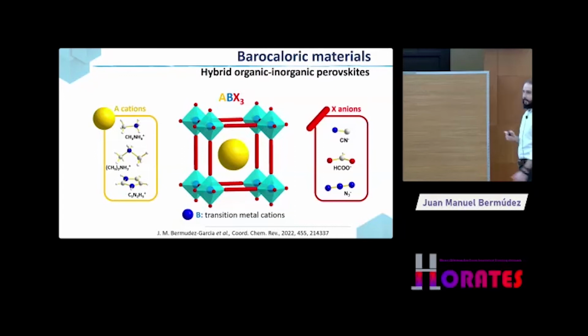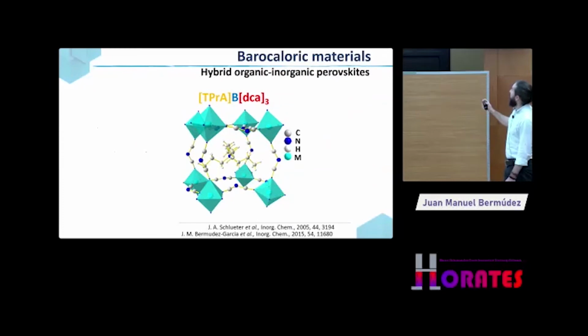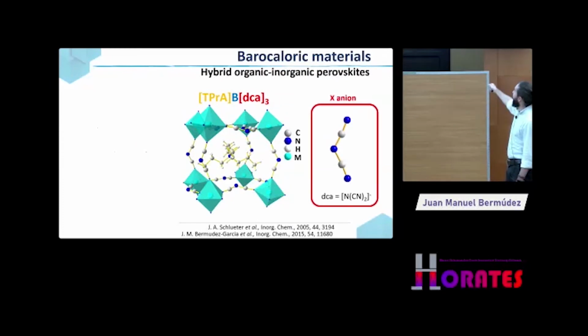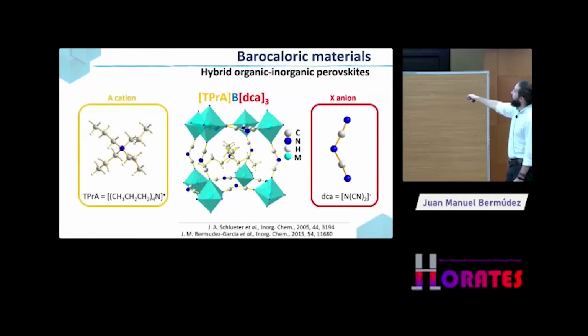And we focus in this kind of materials specifically on a family of materials where the X ligand was quite large. A 5-atom X ligand, called dicyanamide: nitrogen, carbon, nitrogen, carbon, nitrogen. And then the cavity is very large, so we could allocate tetrapropyl ammonium cations. As you can imagine, the reason behind the large responsiveness towards pressure of those materials is going to be the large flexibility of those building blocks. So you can compress those materials very easily.